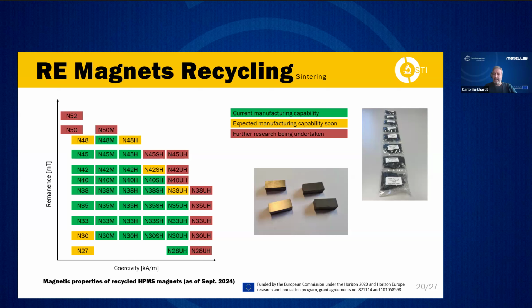I personally see the future of the short loop in the middle range. There are a lot of magnets in the middle range, let's say between N35M and N40SH, where you easily can take recycling material if it's available, and not necessarily pushing the boundaries to these very high performance grades like N50, N52 with 100% recycled material. And here, of course, we will see in future blends that can take as much of the recycling material as possible. And that's one major focus of the Resilience project, to test out the boundaries, how much virgin and recycled material can be alloyed to get stable production of this kind of properties.